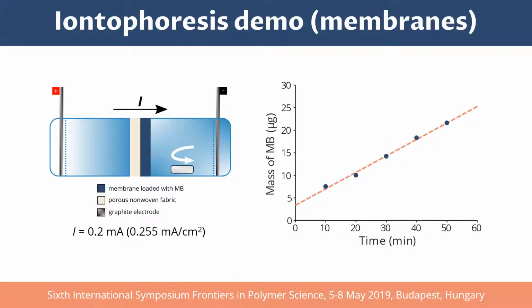We performed an experiment to demonstrate the possibility of active methylene blue release from membranes via iontophoresis. The experimental setup contained a membrane sample loaded with methylene blue, porous mechanical support, and graphite electrodes placed in the side-by-side cell filled with alkaline buffer solution. In this experiment, we achieved the zero-order release kinetics of methylene blue.